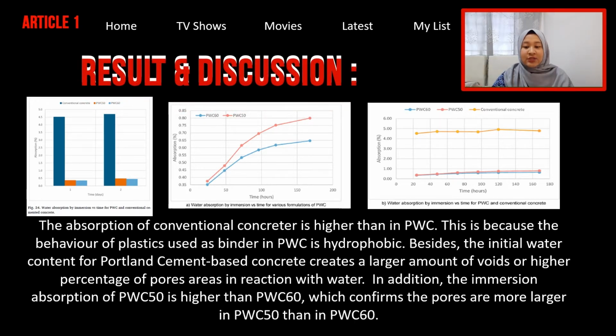From the result, they show that the absorption of conventional concrete is higher than in PWC. It's because the behavior of plastic used as binder in PWC is hydrophobic. Besides, the initial water content for PC-based concrete creates a larger amount of voids, or higher percentage of porous areas, in reaction with water. In addition, the immersion absorption of PWC 50, which is PWC that has plastic content of 50%, is higher than PWC 60, which has plastic content of 60%, which confirms the pores are larger in PWC 50 than in PWC 60.